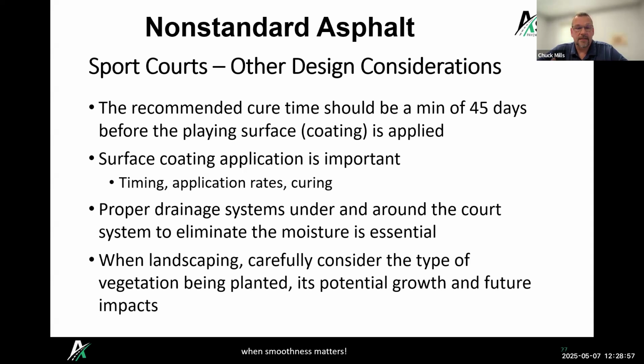And when landscaping and laying out your plans, you got to consider what type of vegetation is being planted and its potential growth and future impacts. If we've got a lot of plantings next to the court, over time they're going to grow up. And if they cause a big shaded area on part of the court, then that can cause issues with water or moisture just sitting on the top of that coating surface and can degrade that as well. So most of the coatings are meant for being out in the sun, being dry and things like that. So all these things, planning is key and drainage and keeping water off is key.